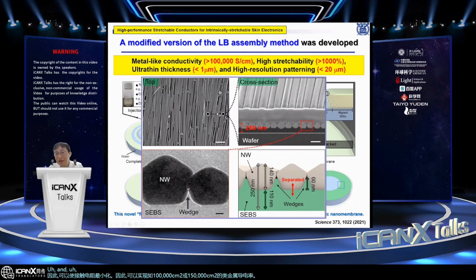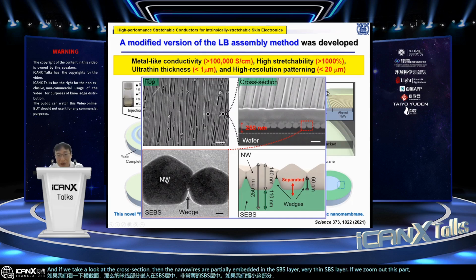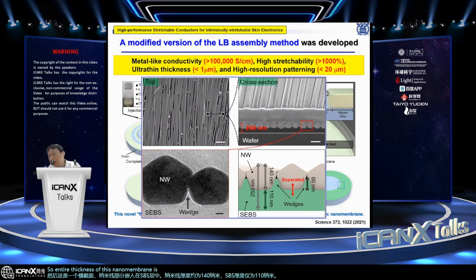And if we take a look at the cross section, then the nanowires are partially embedded in the SEBS layer, very thin SEBS layer. If we zoom out this part, then this is the cross section, the nanowire partially embedded in the SEBS layer. And the nanowire thickness is around 140 nanometer, and the SEBS thickness is only 110 nanometer. So entire thickness of this nanomembrane is only 250 nanometers, so well below 1 micron. So ultra thin stretchable conductor can be achieved.